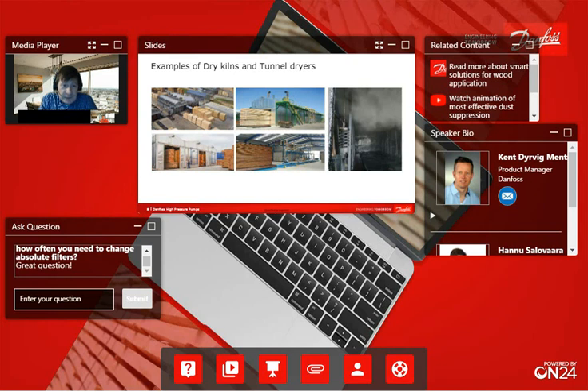Right. Here we have some example pictures. On the left hand, we have these typical drying kilns and tunnels. I think that all professionals following this session can recognize these buildings. On the right hand, we have this latest application, wood heat treatment. It's basically the same as a drying kiln. The only difference is that they are using very high temperatures inside, over 200 degrees. And the gray flying steam above in the picture is this water mist which is sprayed into the chamber. This is a demonstration picture, but it shows very well how this water mist looks inside. And of course there are fans which rotate this water mist when this chamber is in real action.